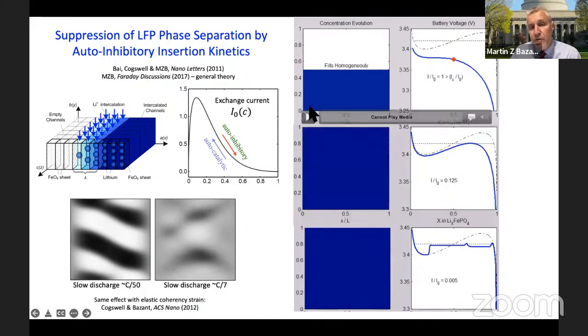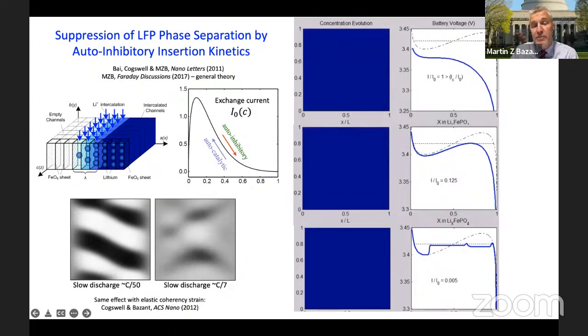And in this model, if you go to an even higher current, then at some point phase separation is completely suppressed. Although if you stopped the current at a certain point in the miscibility gap, you would recover phase separation. So simply the application of the current changes the thermodynamics of the system far from equilibrium. It's a very interesting phenomenon.